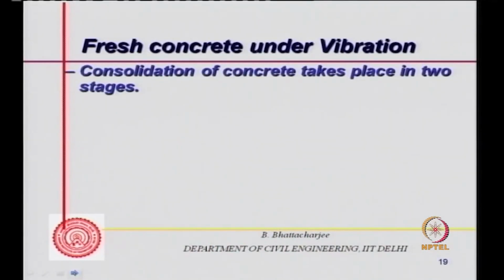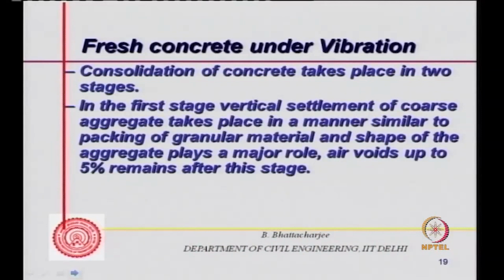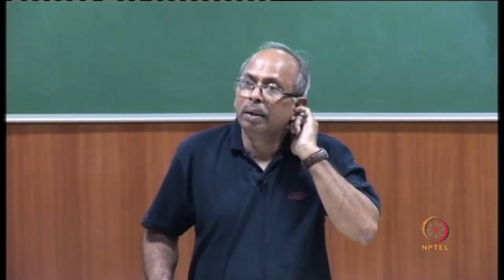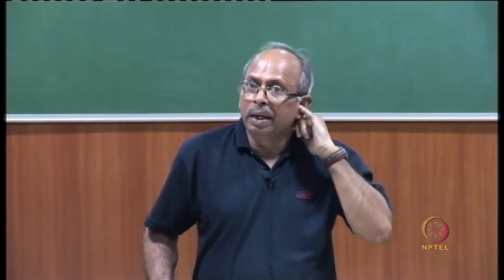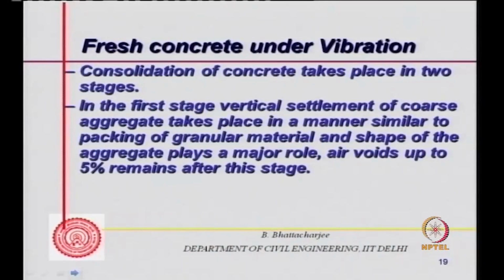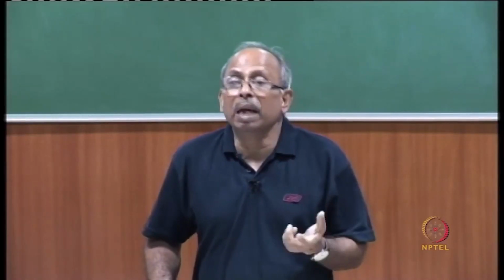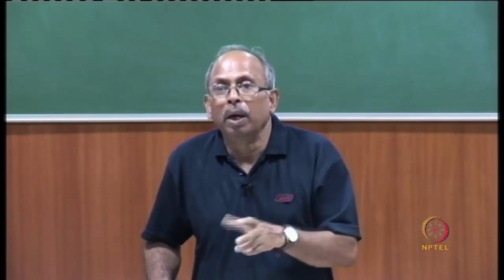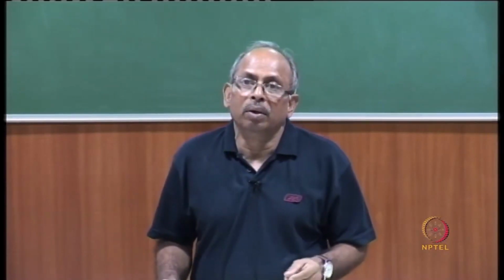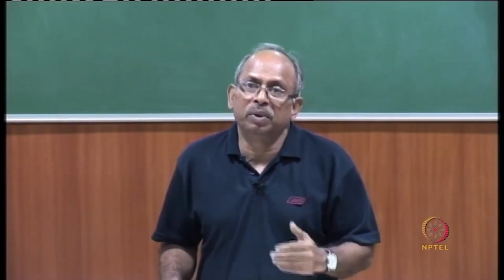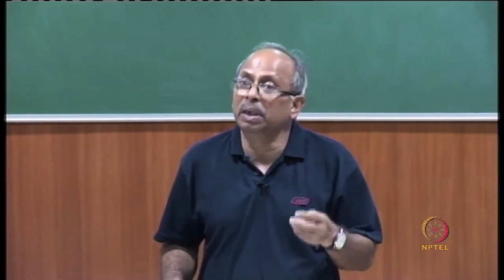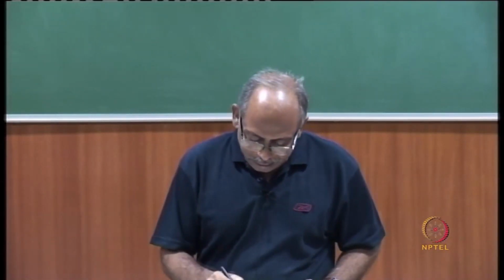Fresh concrete consolidation actually occurs in two phases. In the first stage, vertical settlement of coarse aggregate takes place in a manner similar to packing of granular material, and shape of the aggregate plays a major role. Air voids up to 5% remain after this. Spherical particles will easily roll over, and therefore, in the first stage itself, vertical settlement becomes easier for rounded aggregate.